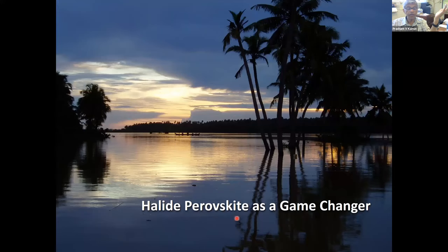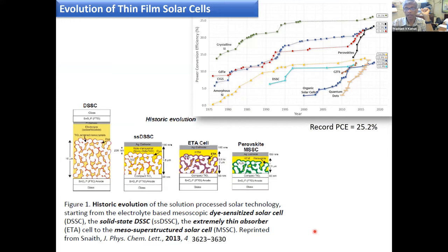As I mentioned, after 2012 the perovskites came in and changed the whole game of these semiconductor nanostructures. What we started with, dye-sensitized solar cells in the 90s, then became solid-state dye-sensitized solar cells, extremely thin absorber, quantum dot solar cells, and then the perovskite solar cells. Two things to take into account. In the beginning, we had to use an electrolyte as a hole transport layer to recycle these. And then for solid state, people used spiro-OMeTAD and showed that solid-state DSSCs can be constructed. So all this understanding helped to advance these perovskite solar cells.